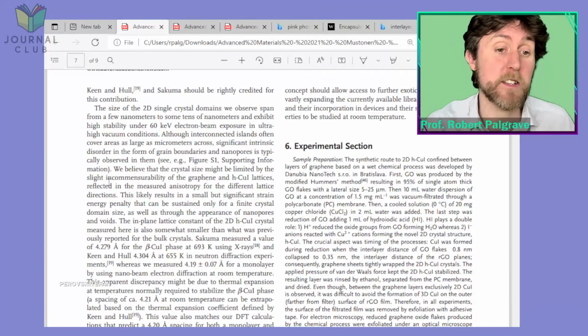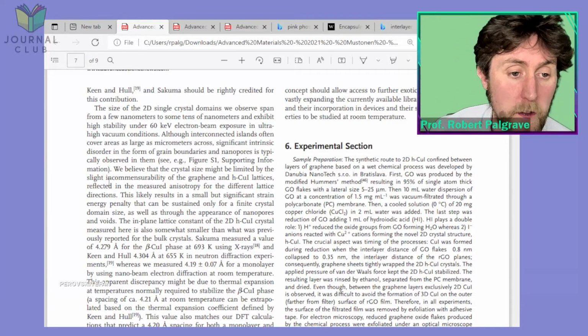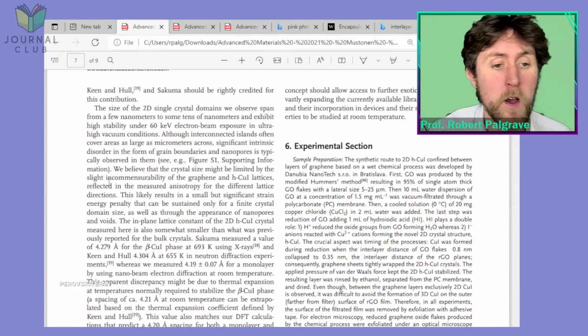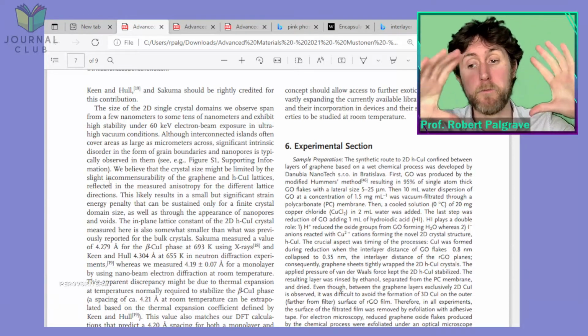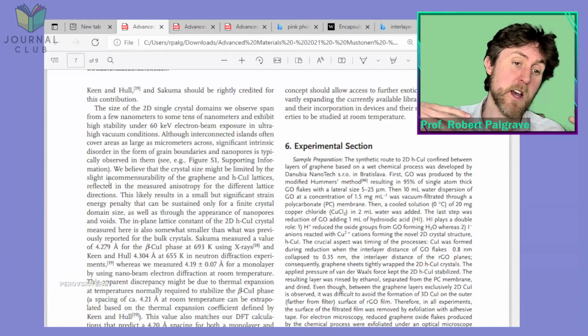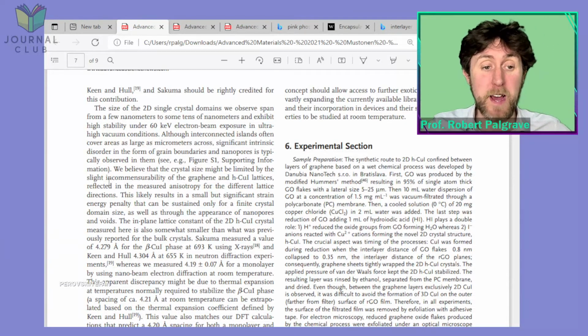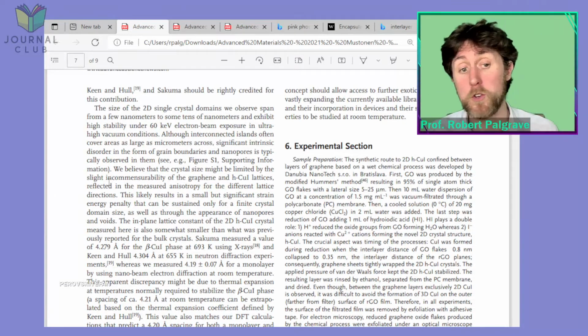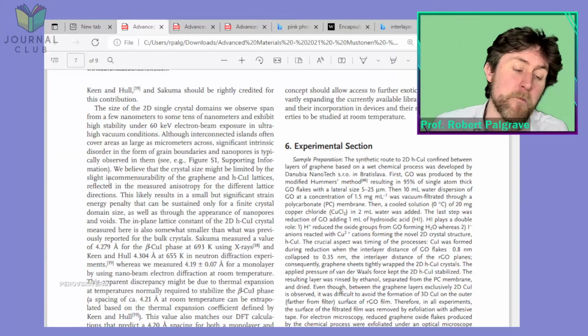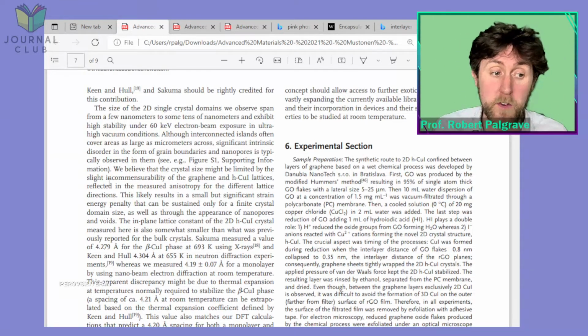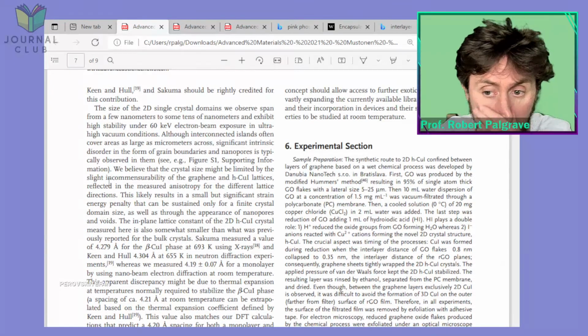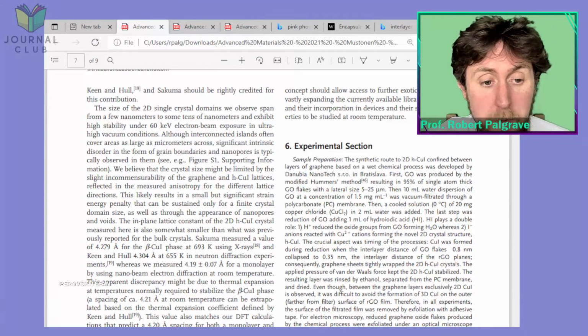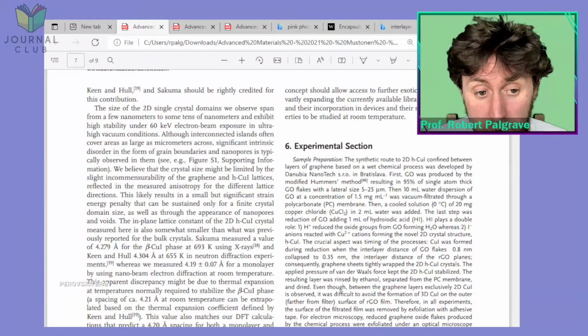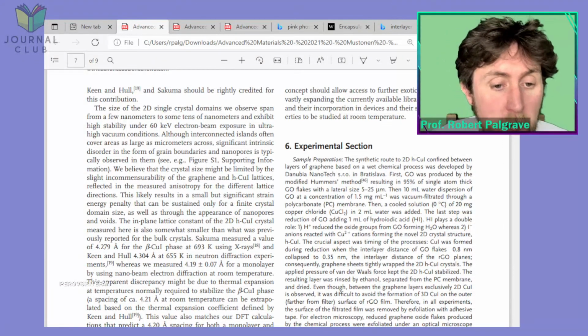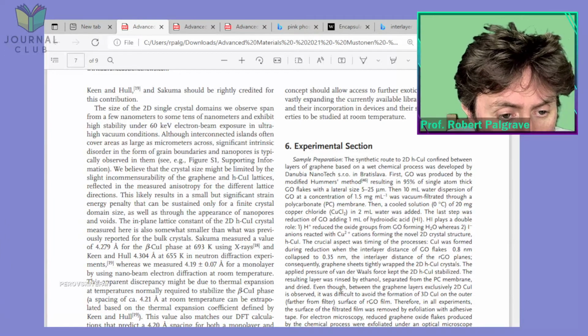So these are ideas that are commonly found in thin film epitaxy as well. You have to stretch one of the lattices to make them line up. That introduces strain energy. The bigger you make that domain, the more strain energy you have, and eventually the strain energy is going to be too big to accommodate, and it's going to fall off. You're not going to be able to maintain that structure anymore. So it will break up into other things, or you'll introduce defects, things like that.